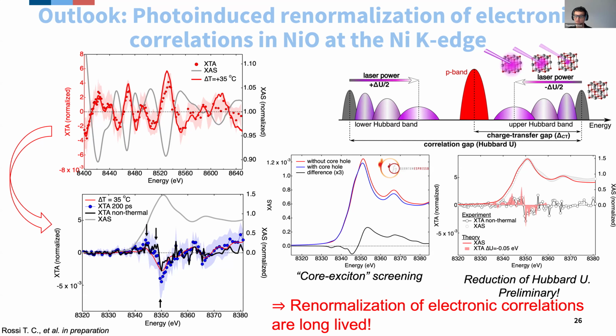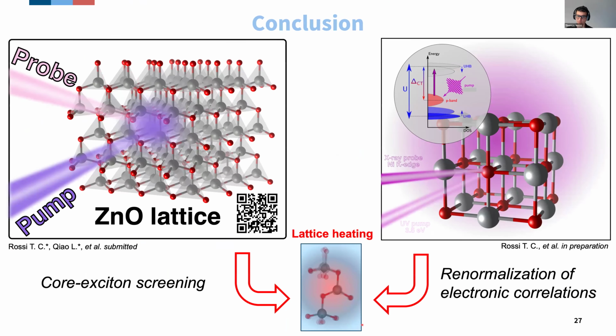And these correlations are actually long-lived, which is the question that we tried to address at the beginning. For how long can we actually use them for actual applications? So they can live for at least 200 picoseconds, and the kinetics indicates that they live for at least several hundreds of picoseconds before they recover. And that was basically an outlook. So now I would like to conclude.